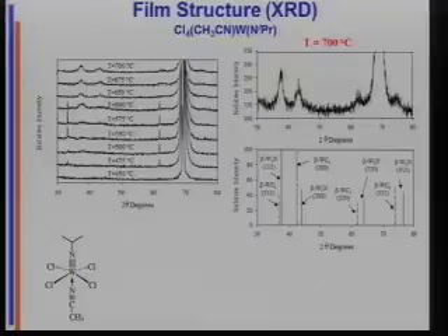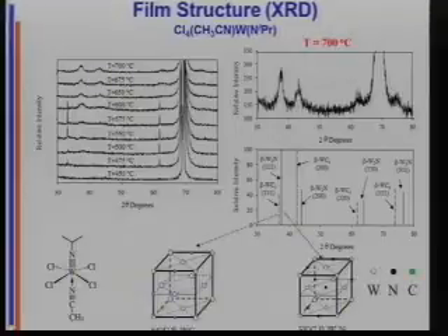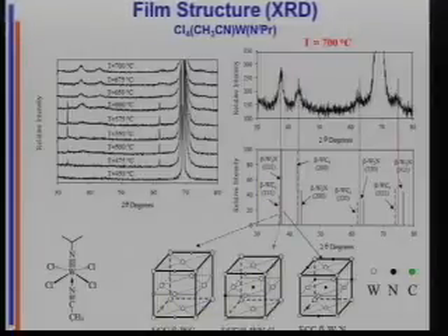Okay? And here's the temperature equals 700. Here are the standards for tungsten nitride and tungsten carbide. I am still worried about the carbon, right? So I check these. You'll notice that these XRD patterns look very similar, and that's because the majority of the diffraction is off the tungsten atoms, and you have the same tungsten lattice for both of these. The sublattice is occupied here by carbon, here by nitrogen, and what we grow is somewhere in the middle. It's the ternary phase, okay? So we have our sublattice occupied by some nitrogen, some carbons, and some vacancies.